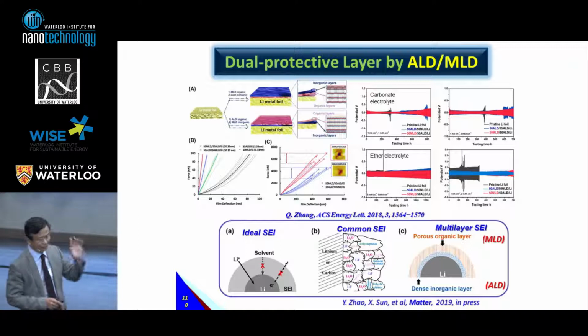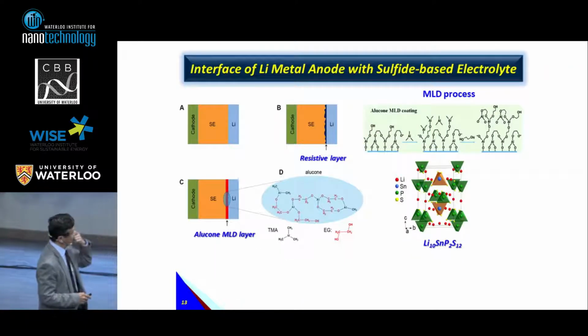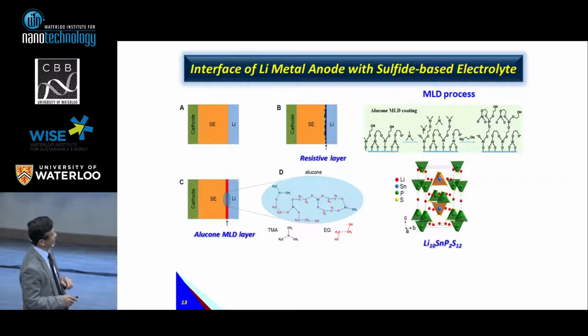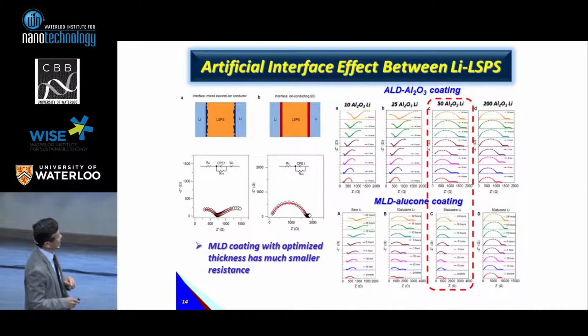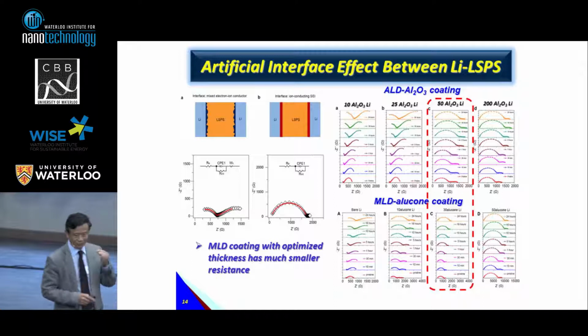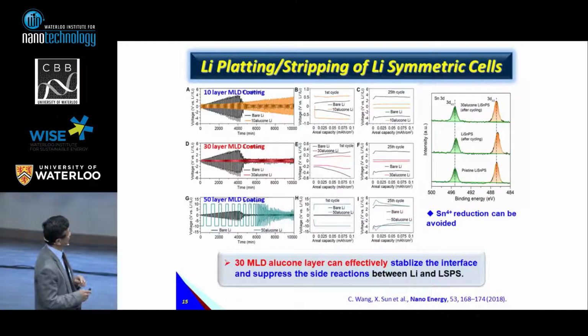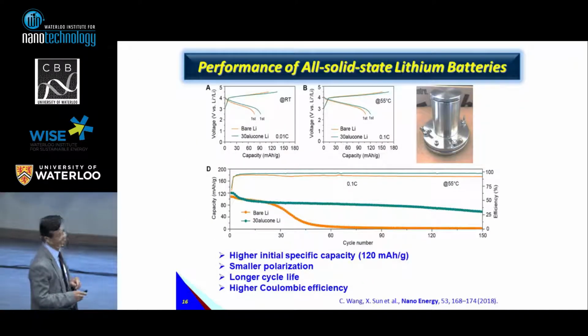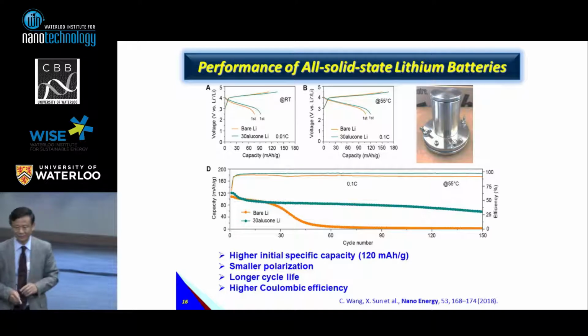So when we use the same strategy and move to solid state, we pick a solid-state electrolyte. We use that coating, and we found the resistance is much smaller, and particularly here it is very stable compared with no coating. And also you have a full cell battery. You test it, and you found that without coating it just runs 30 cycles and died, but with the coating, you can have a good performance.